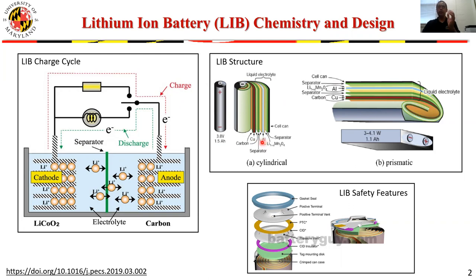They are separated by a thin plastic separator that prevents the two from touching each other and thus undergoing direct reactions. They are soaked in electrolyte that provides the transport media for the lithium ions, and then sealed airtight in a typically steel can. They vary in shape and size. Most typically it's either cylindrical or prismatic. And I forgot to mention that the roll that goes into that can is typically referred to as a jelly roll.